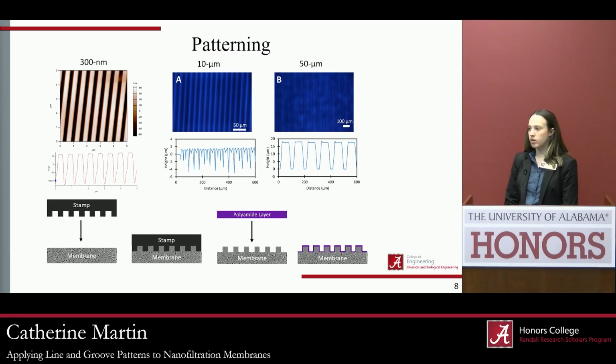So when we were doing the profilometry, sometimes the tip didn't get fully in the grooves, because they were too tiny to sometimes get fully within the grooves for the profilometry, so that's probably what you're seeing. But also, we wanted it to be 10 micron deep, 10 micron across. It wasn't always 10 micron deep with this stamping because we use thermal embossing, but it was pretty close.